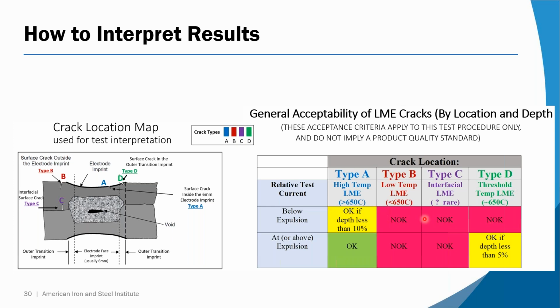Above expulsion, we have the chaos factor, so the accept-reject criteria change a bit. But basically, we never want to see type B. Type C, you don't see very much, but if you do, it's not okay. Type D, if it's above expulsion and shallow, that's understandable, acceptable. Type A cracking will be accepted at any depth if it's above expulsion. Below expulsion, we only want to see superficial type A cracking.